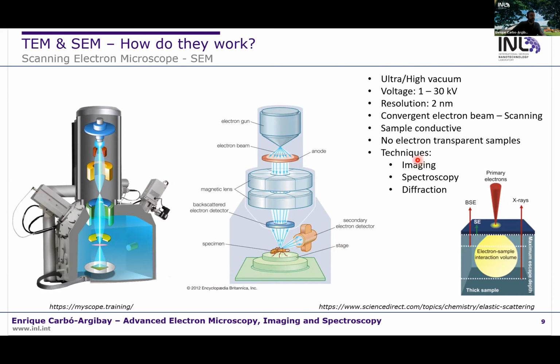What are the main features of this technique of scanning electron microscope? Basically, the resolution we can reach in terms of imaging resolution is 2 nanometers, even 1 nanometer. The sample must be conductive, but this is not a problem. We have sample preparation equipment to make the samples conductive, depositing a layer of metal or a layer of carbon on the sample. We can make it easily conductive, and the samples don't need any additional preparation. So we don't need thin samples or other specifications. So we basically can take a bulk sample, place it in the sample chamber, and scan the sample with the electron beam. The resolution, as I told you, is around 2 nanometers.